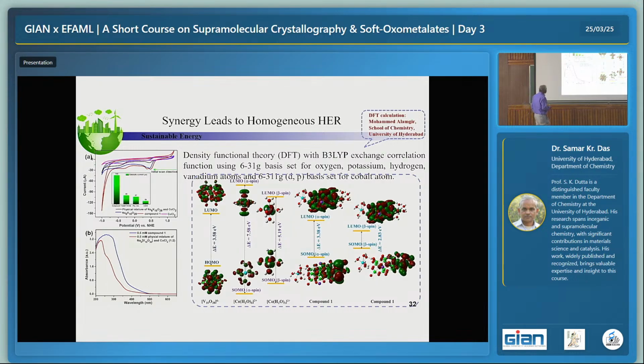So this is the HOMO-LUMO gap of the cluster. Now cobalt 2 will have two spin states, alpha state and beta state. The beta state gap is smaller than the alpha state. For our compound, the one we got as single crystal, for the alpha state this is the gap, and for the beta spin this is the gap, which means beta spin is better. A synergy is established when you get this. They talk to each other, because the vanadium cluster and the cobalt system talk to each other. Only when synergy is established does it happen.